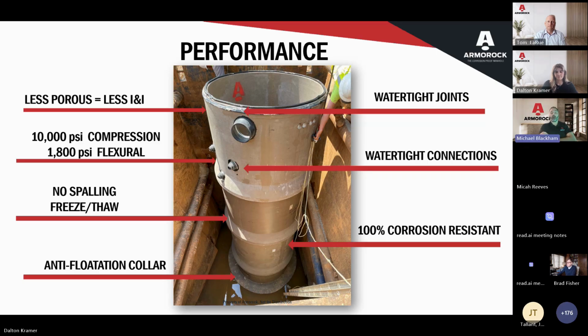Armorock specific structures are also engineered, as you see there, to exceed traditional concrete in both compressive and flexural strength. Our manholes, we build and design them to exceed 10,000 PSI 28-day compressive strength, and over 1,800 PSI flexural strength. This is at least 2 times over what the specified value of traditional conventional manholes are. We also have joint systems that are designed for watertight performance. And actually, industry standard vacuum testing on a manhole is 10 inches of mercury vacuum pressure. We have actually tested our manholes at our facility to twice that. So we have a very, very tight, watertight product.